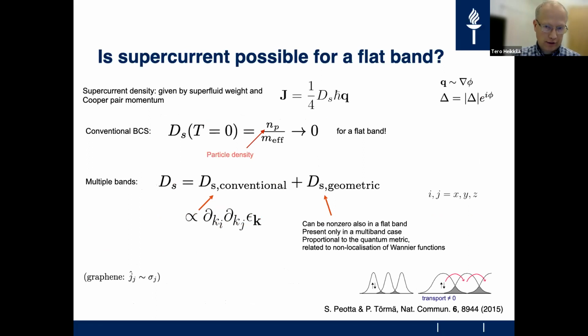Okay, now I have discussed the fact that I want to discuss superconductivity on a flat band, and one thing is, of course, to consider this mean field gap. But can the electrons on such a flat band actually give rise to superconductivity? Superconductivity does not only require that the gap is finite, but also that there is a finite superfluid weight, this D_s here, which is the prefactor between the supercurrent and the phase gradient. In conventional BCS theory, the superfluid weight is proportional to the particle density divided by the effective mass. And this effective mass diverges for a flat band, which means that the Cooper pairs in this case would be completely localized, and they couldn't carry any current.